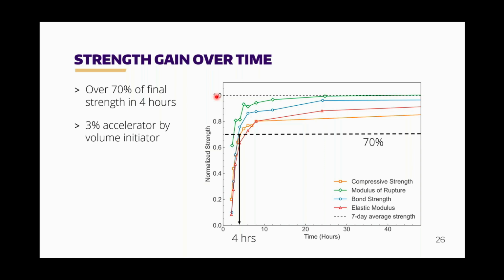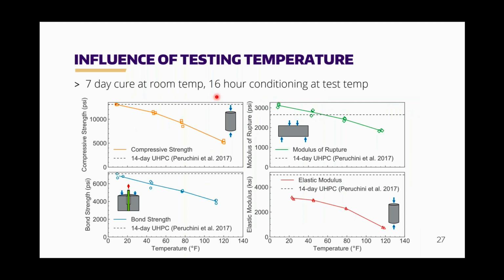The next variable that we looked at was testing temperature. I really want to highlight that this is the testing temperature, not necessarily the curing temperature. So these were cured for 7 days at room temperature and then conditioned for at least 16 hours at the testing temperature to ensure that the entirety of the specimen had reached that test temperature. This is something that would maybe mimic more in the field something that's poured during a quote-unquote usual temperature, and then you're seeing these results at the extreme heat of summer or the extreme cold of winter, but one where they were placed at a more average temperature.